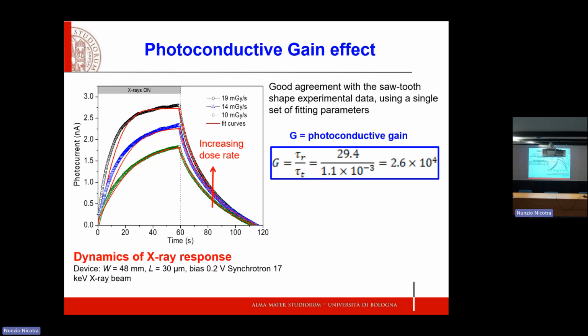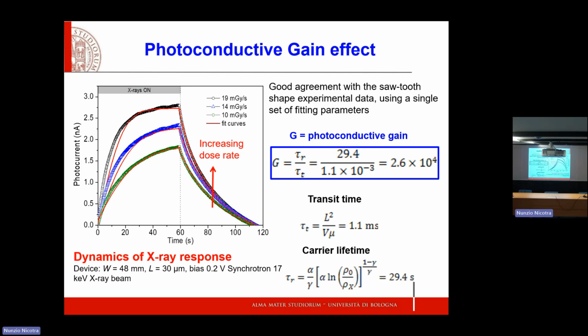And this is how we could actually also control this effect by modeling it. And we can model this photoconductive gain as the ratio between two different phenomena. The first one is the transit time across the device. So the geometry of the device makes a difference. And the second one is the carrier lifetime. The carrier lifetime is severely controlled by the trapping states, energy and distribution. So if we introduce these parameters into this analytical expression, we can very nicely model the response, in this case shown for an increasing dose rate, of our very thin organic film to X-rays.